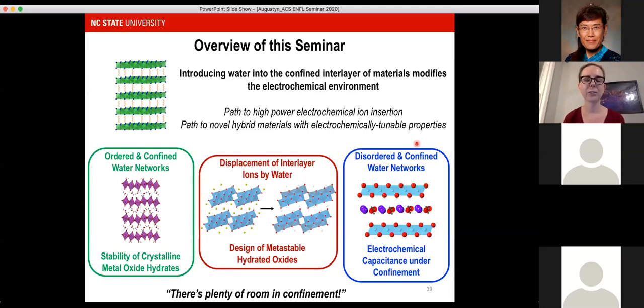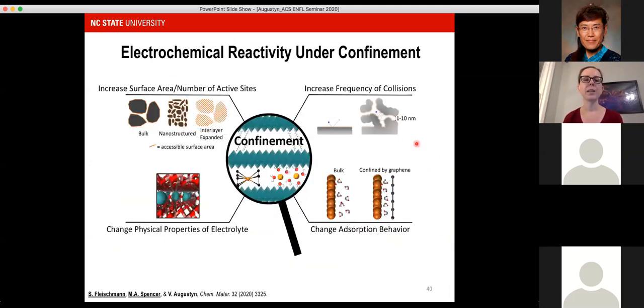I think there's a lot of really interesting electrochemical phenomena to discover, and that includes electrochemical reactivity. So instead of looking at just things like alkali ion or proton insertion for energy storage processes, we can also start to look at things like electrochemical reactions under confinement, because what happens under confinement is that we can start changing the physical and adsorption properties of whatever's confined in this interlayer region. And layered materials are actually very ubiquitous in theoretical studies of what happens during confinement. And I think we're at the stage where now the synthetic prowess is there to start validating those theoretical predictions with experimental results.